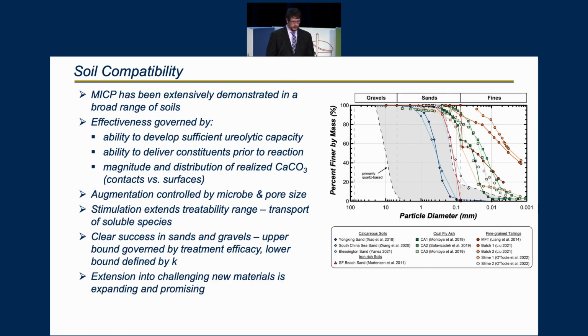When considering the breadth of studies that are out there, what we can see is that there is clear success in a variety of different sandy and gravelly materials, with the upper bound particle size largely governed by practicality and treatment efficacy considerations, and the lower bound particle size largely governed by limitations related to low hydraulic conductivities. What we can also see is that more recently the field has extended into challenging new materials such as tailings and combustion residuals, and of course this is quite promising and exciting moving forward.